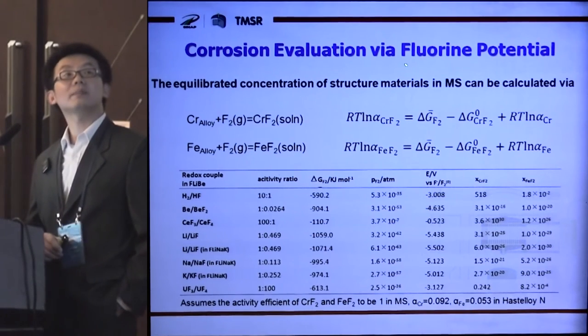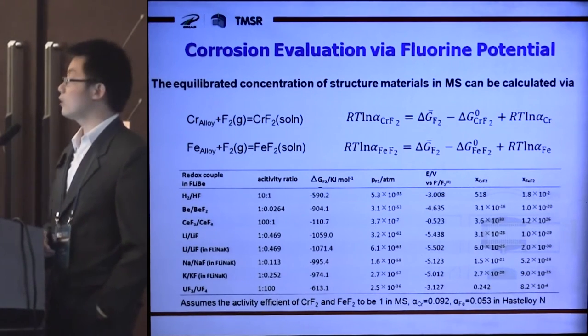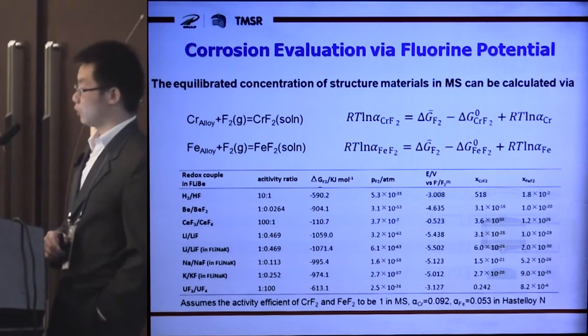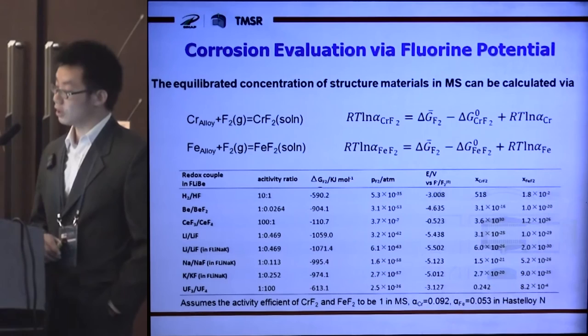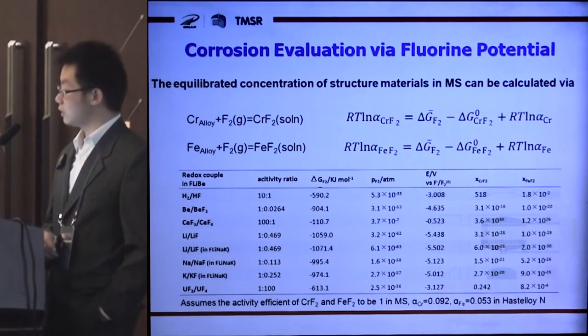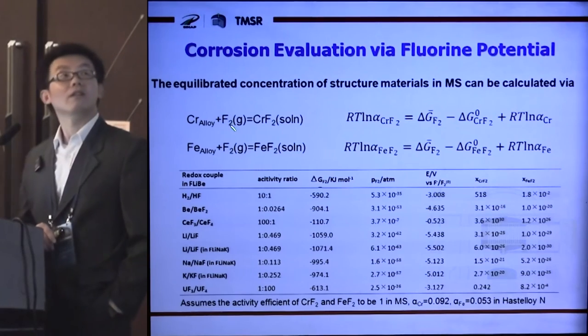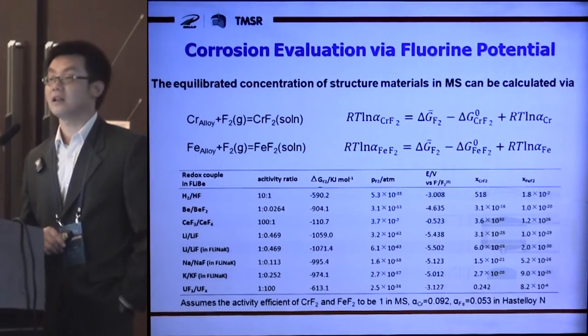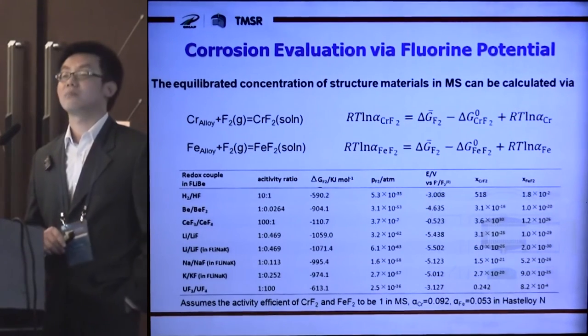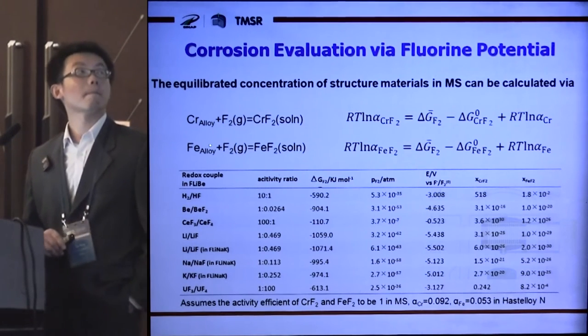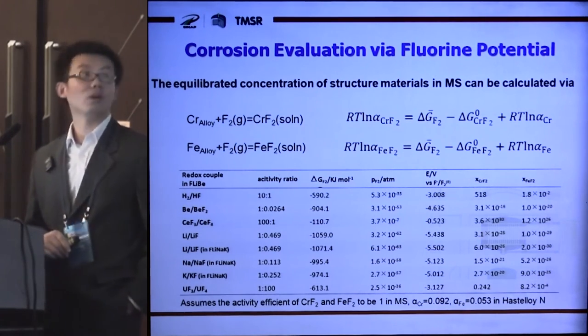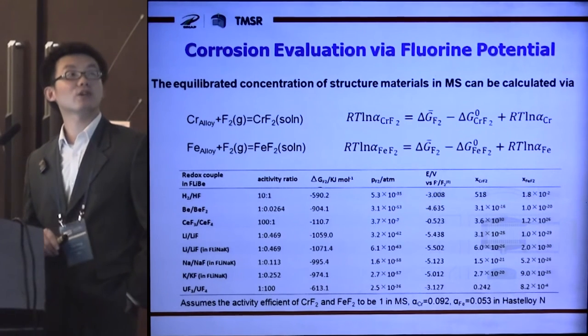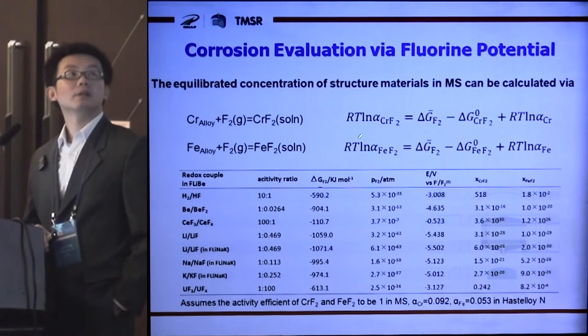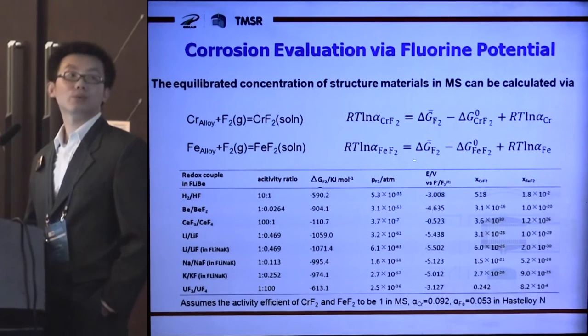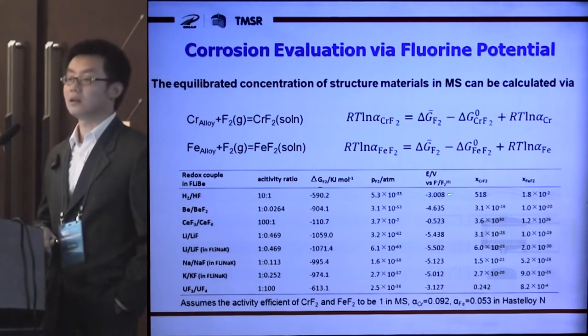With the concept of fluorine potential, we can evaluate the corrosion ability of the molten salts. The equilibrated concentration of structural materials in molten salts can be calculated via these reactions. We take chromium and iron as examples because they are the most easily corroded elements in a nickel or iron-based alloy. The calculated mole fraction of CrF2 and FeF2 were listed in a table.